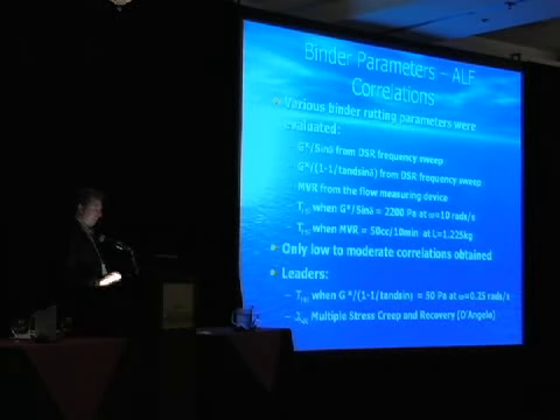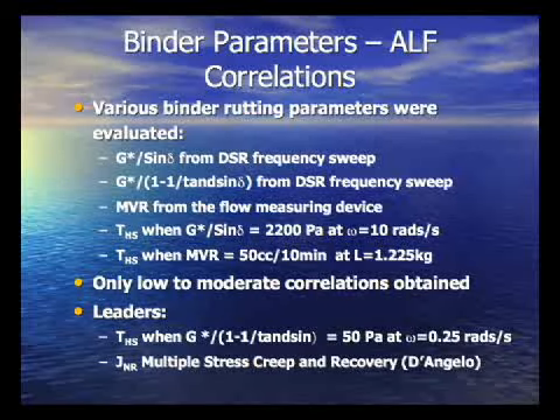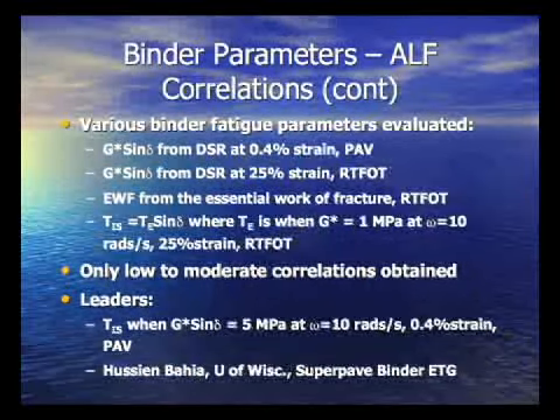In terms of binder parameters correlating to the ALF for rutting, we've looked at a number. And we've used the Superpave binder ETG to vet these binder characteristics. Low to moderate correlations are obtained, but the leaders in terms of this are this high temperature spec that was based from Arun Shenoy, our rheologist. It's a modification of the spec, but you're also looking at different stiffness. It's probably the easiest to be implemented, while John D'Angelo, this is his passion, he's looking at this multiple stress creep and recovery. That is also coming to fruition soon.